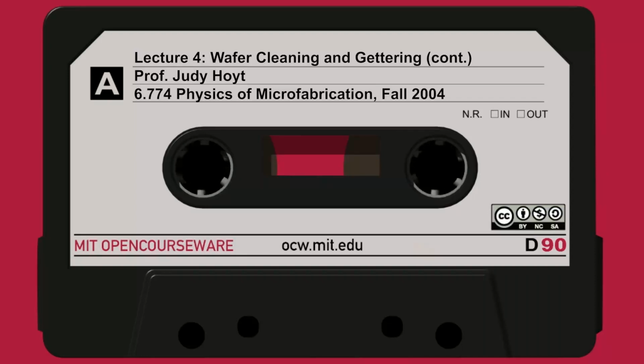So in substitutional form, we know that gold introduces deep levels in the band gap near the mid gap position. In fact, there's one here, an acceptor level marked here, and there's one here, a donor level marked there. So this Au minus level is going to be created whenever the gold can capture a free electron. So if there's a lot of free electrons, we can create this Au minus state, this acceptor level. So I can just write down this simple chemical equation: one gold atom plus an electron goes to an Au minus ion.